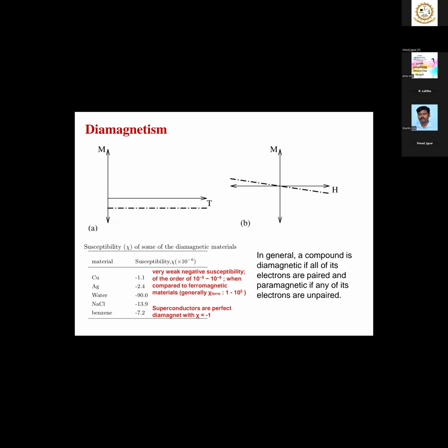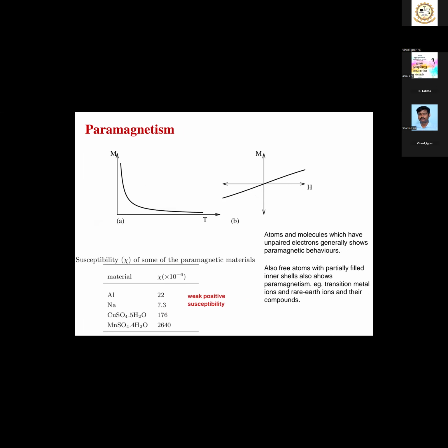You can see for a diamagnet, magnetization will be slightly negative, so it will be a very weak negative susceptibility. And magnetization with respect to field also: when you increase the field, magnetization will fall down. And for a paramagnet, the trend is like this. When you cool the paramagnet to a low temperature, magnetization will increase. This trend is called 1 by T behavior: magnetization will be inversely proportional to the temperature. With respect to field, if you increase the field, magnetization will slowly increase, but there will not be any saturation. And susceptibility will be positive and weak.